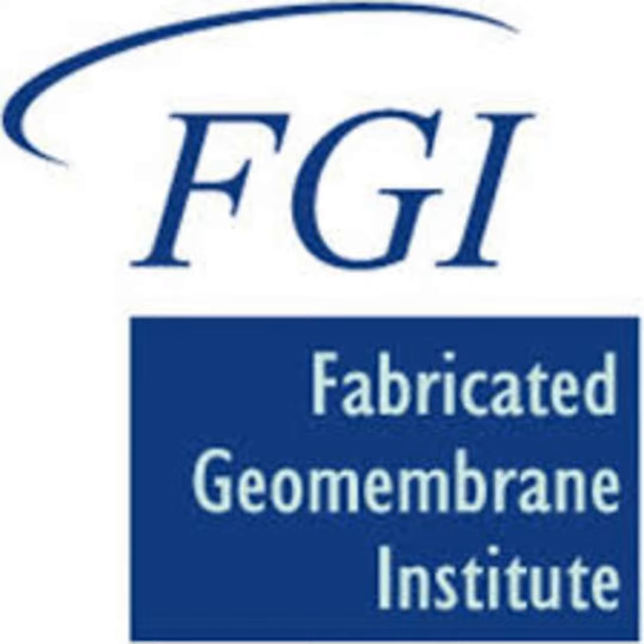Tim, I don't know if you want to add some other thoughts in there. You've done a lot of work in this area too. Yeah, I think you hit on the main mechanisms. I think the reinforcing fibers just finally get tightened up, and then that gives a little peak, and then they sort of start behaving all together after that. So there may be, I don't know, 10%, 15% that sort of engage before all the others, and maybe that's that little peak. It's really not that big, but it is interesting.